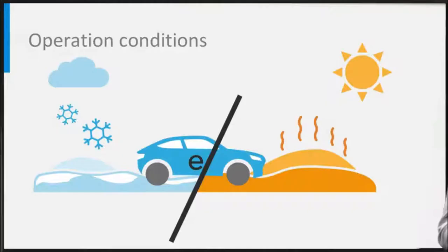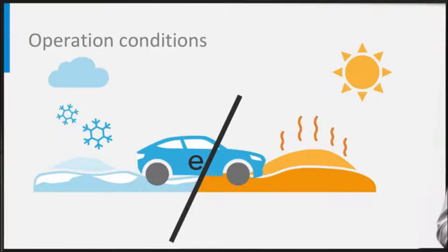The operation conditions of lithium-ion batteries also have a large impact on battery cycle life. High temperatures enhance electrolyte decomposition, which, as discussed, is detrimental for the cycle life. High temperatures can occur due to the outside temperature, but also because of the heat development in the battery simply due to the internal resistance. This may require active cooling to guarantee a long cycle life. Low temperatures increase the internal resistance, which effectively lowers the power and energy density of batteries, but only when kept at this low temperature.